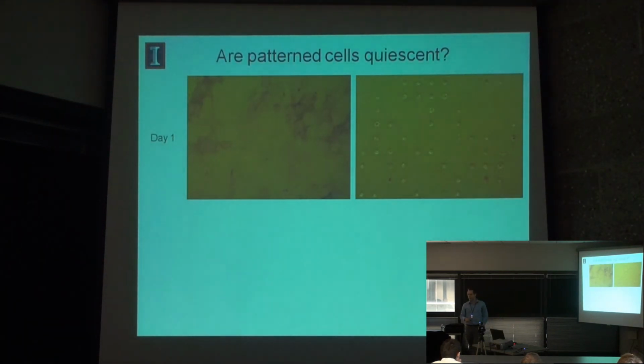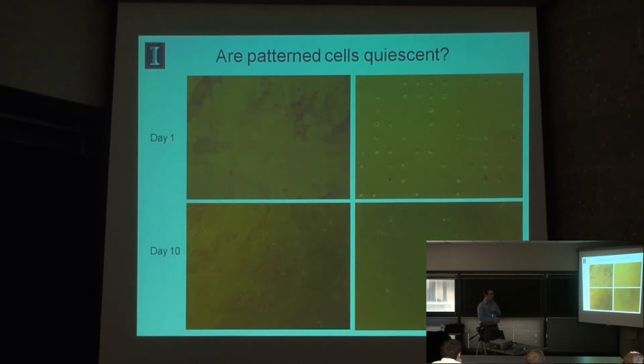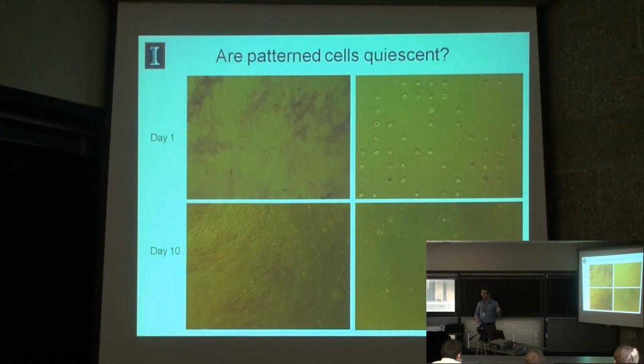This is just a news story that's come out that I think is interesting, and it revolves around this idea that came a bit out of a serendipitous discovery, where we patterned cells and they were left, and these chemistries on gold are not so stable. And so cells can migrate and leave them after about a week. And these were left for too long, and so they migrated out. And they were fixed and stained anyway, thankfully, because we saw something really interesting: when cells, as we culture them normally, are allowed to divide, they express alkaline phosphatase, but when they were patterned, after they escaped, they're no longer expressing alkaline phosphatase for whatever reason.